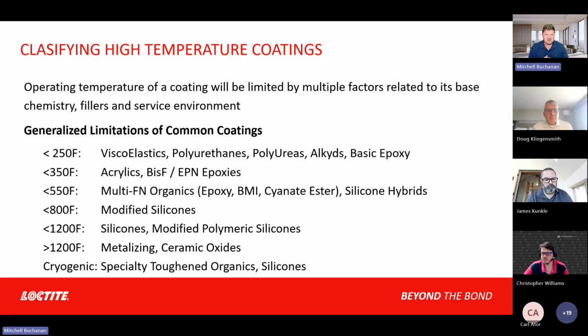You get into the bisphenol F and Novolac epoxies, and most of those are going to have a continuous operating temperature, especially for immersion service, around 350 degrees Fahrenheit. And then you get into the specialty multifunctional organics, like BMI resins, multifunctional epoxies, so glycidylamines, and then cyanate esters. Those can reach continuous operating temperatures of 300 C. You'll see it thrown around a lot that organic coatings top out around 180 C or 200 C. In coating space, most coatings that's pretty true because viscosity becomes an issue, right? But if you're doing plural component type coatings, or you're looking into composite repair type stuff, like our high temperature pipe wrap, those are organic resin binders, and they're going to have 250 to 300 C continuous operating temperatures.